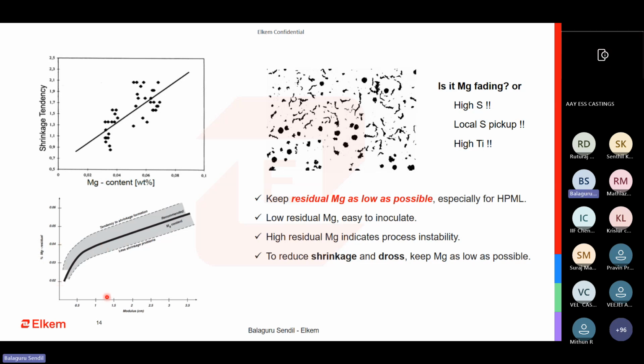These are charts prepared by both Sorel Metal and other very reputed organizations, in a paper published almost 20 years back, and it still holds its value. So the magnesium must be very, very low. You don't need high Mg, especially if you're going for high pressure molding lines, Sinto, whatever it is. If you're operating at higher levels of magnesium, then the possibility of having dross, shrinkage and carbides is very high.